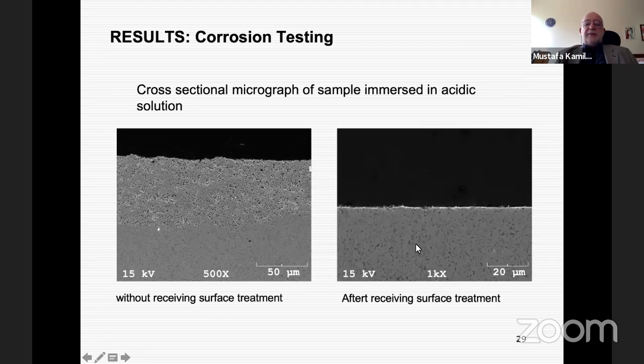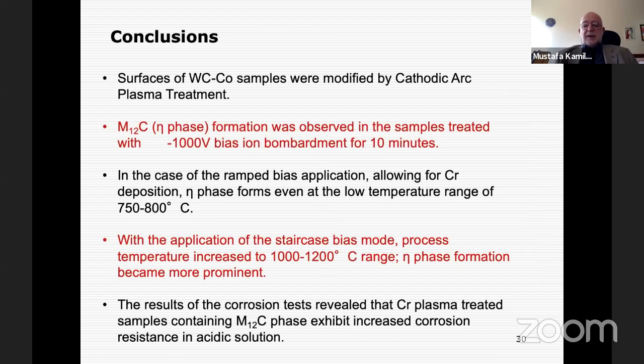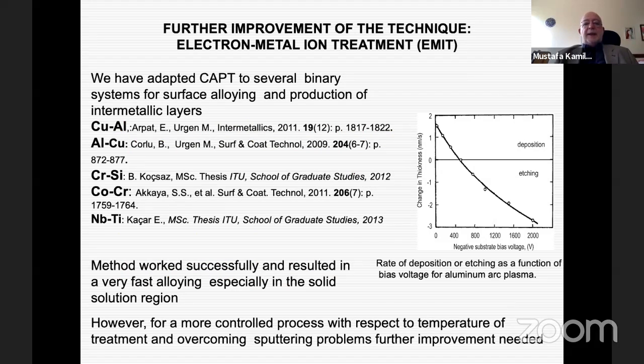So when we do the same test with the samples that have been treated, we didn't observe any of this process taking place. So it showed us that we successfully managed to alloy the surface, alloy the cobalt phase in the tungsten carbide cobalt samples for improving their corrosion resistance. And we have a registered patent on this story. And then we continued to study different alloy systems by using the same methodology.